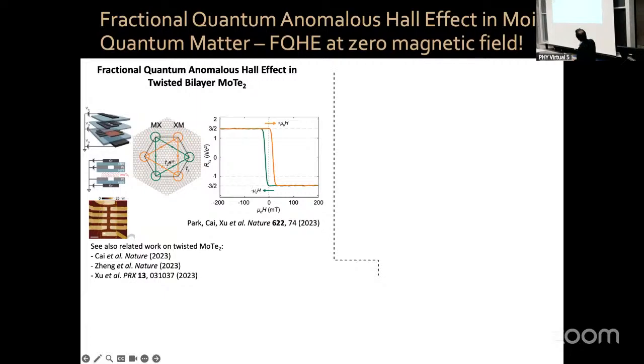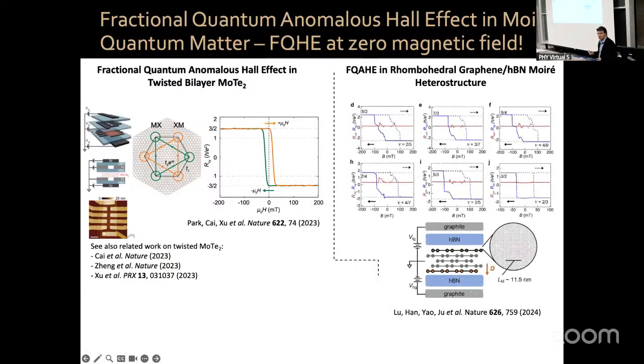The following year, my colleague Long Ju at MIT and his group measured the fractional quantum anomalous Hall effect in a different Moiré heterostructure, called rhombohedral graphene—without a twist angle, but with particular stacking of the graphene layers aligned to hexagonal boron nitride to make a Moiré pattern—and then measured other different fractions.